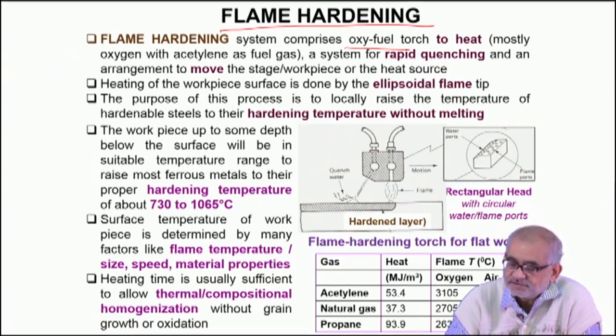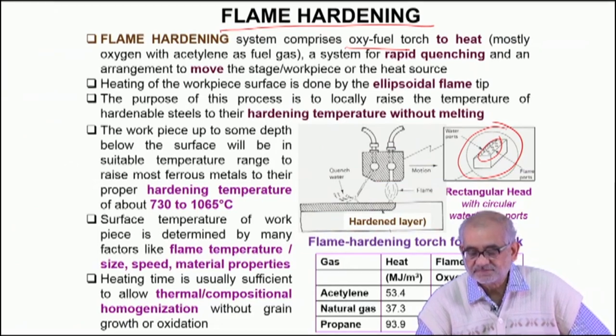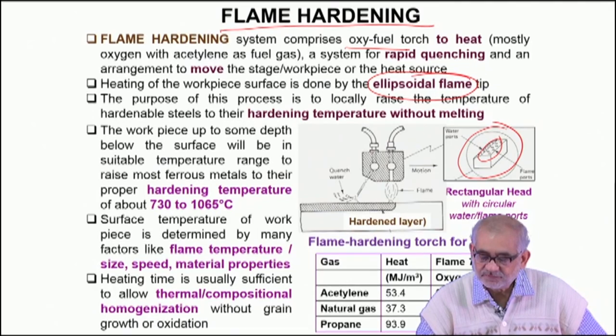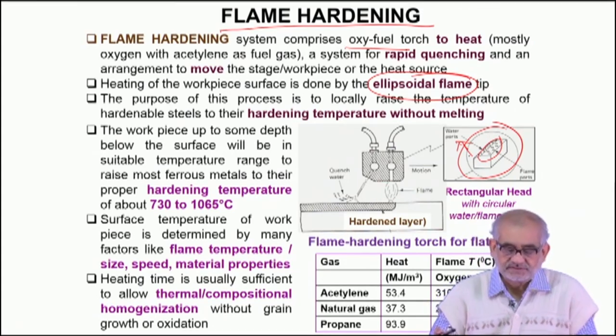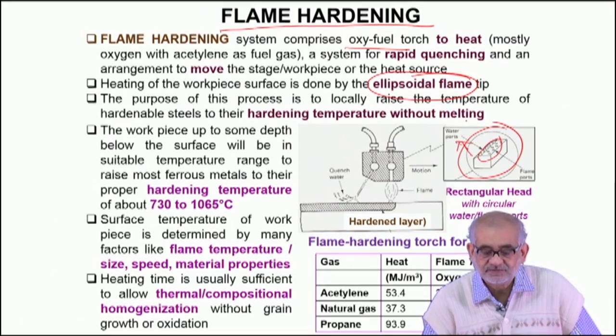We use a burner — a typical burner with several orifices. The top portion creates high temperature through combustion of the oxygen-acetylene gas mixture, and the tip assumes an ellipsoidal form. From the sides of the burner nozzle there are additional orifices through which water can be thrown. When the flame is off and the surface of the stock has reached the required temperature, immediate quenching is obtained by throwing water or coolants such as water-salt mixtures, water-polymer mixtures, or oil. This fluid flow extracts heat from the surface and causes very fast quenching.